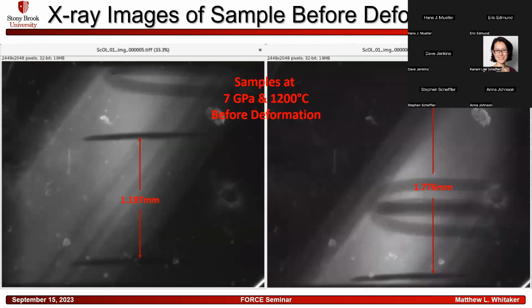So what do we see from this type of data? Well, in the X-ray images of the sample, we can see that in this particular cell assembly, there are two samples present. The one on the left is the bottom sample, and that's just under 1.2 millimeters in length. And then there's the top sample that is just over 1 3/4 millimeters in length. This is at 7 GPa and 1200 degrees C.